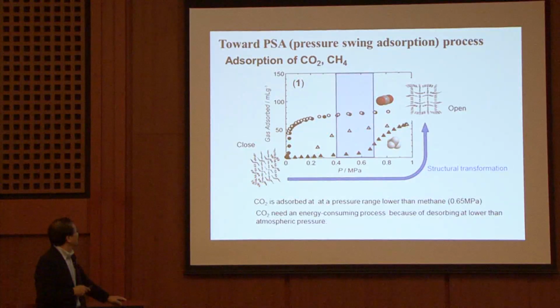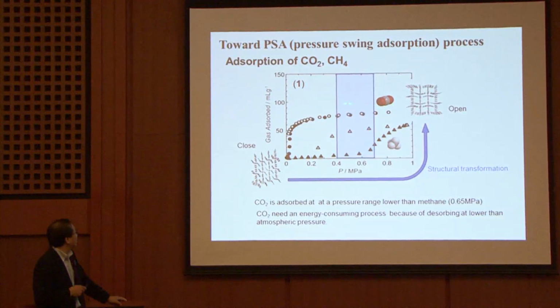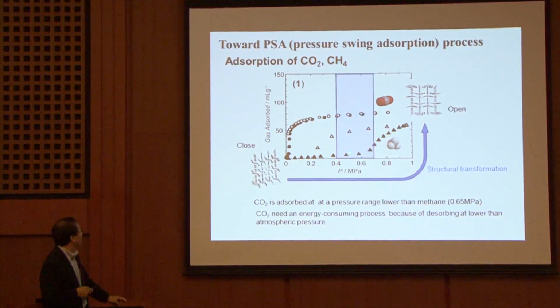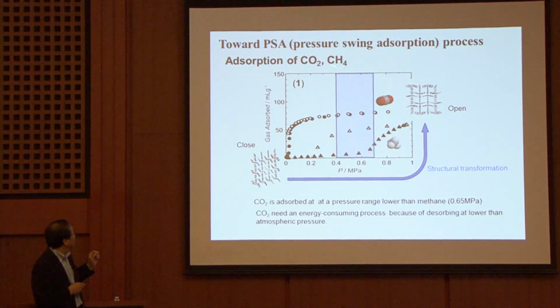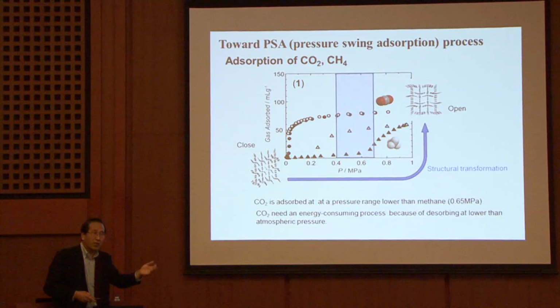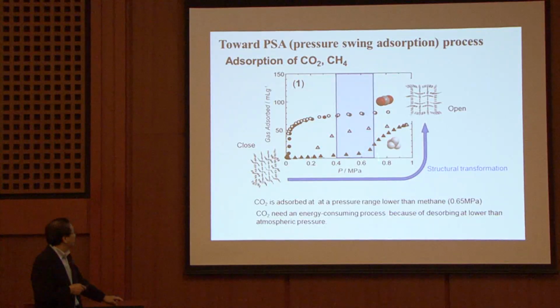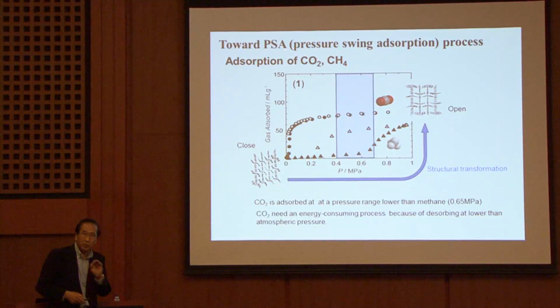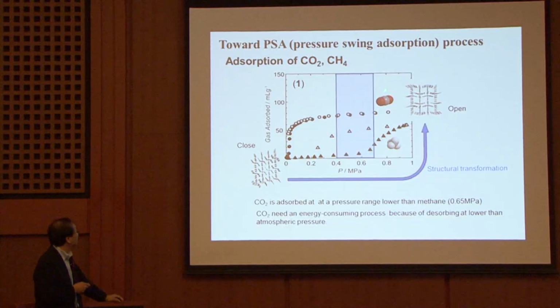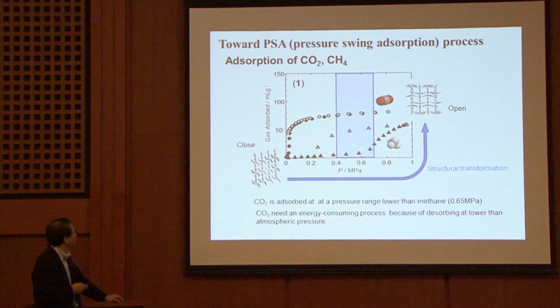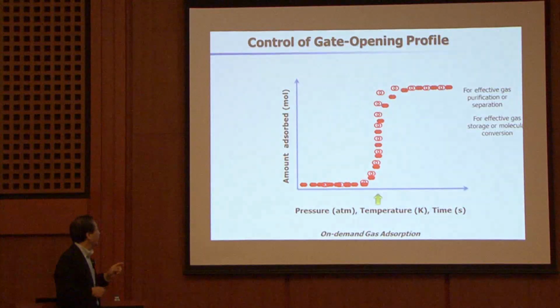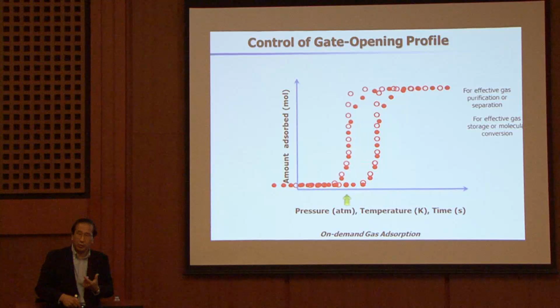The other kind is natural gas, biogas. Methane and CO2 are like this, the same thing I just showed you. But usually, the industry uses this kind of pressure swing adsorption process. Pressure swing means higher pressure and reduced pressure. So the pressure range is 0.4 to 0.7, because in these regions it takes more energy to remove the gas molecules. So this is very important. But you see, CO2 cannot get removed in this region. It's not a good way. We have to change the gate opening pressure.